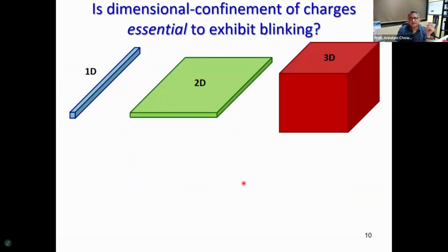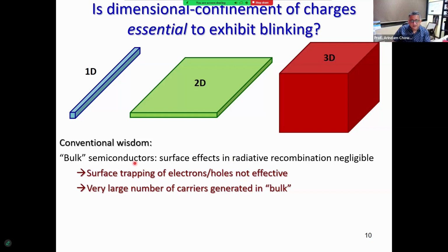So one of the questions that we were thinking about at one point of time is, what happens to larger structures, such as 1D materials or 2D systems or even bulk 3D systems. And conventionally, you would imagine that bulk semiconductors would not show this kind of blinking behavior because, first of all, the effect of the surface is negligible. Okay, it's dominated by the bulk. And what that means is that most of the carriers that are generated would recombine in the bulk. And the second is that even if there is some sort of trapping happening locally at different spatial locations, you can see in this 2D crystal, they will be trapped at different points of time. And therefore, I will observe a heterogeneous fluctuation of intensities.